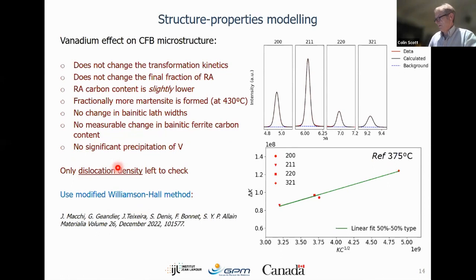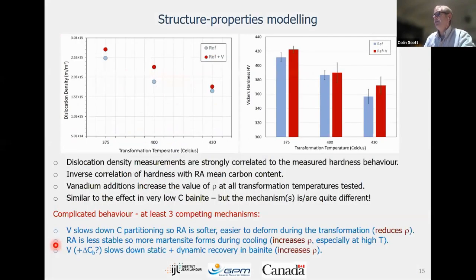Excuse me, my time's nearly up. So we use Williamson Hall to do that. And so this is some of the raw data. And the result is shown in this graph here. So here are the 3 transformation temperatures, 375, 400, and 430, with the 2 grades. And you can see that the vanadium grade has systematically higher dislocation density. Compare that with the hardness data, they could almost be superimposed. Almost, not quite.